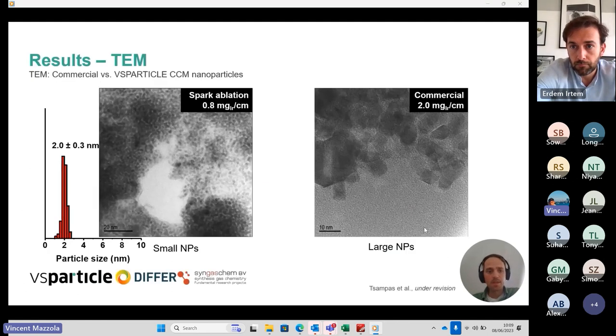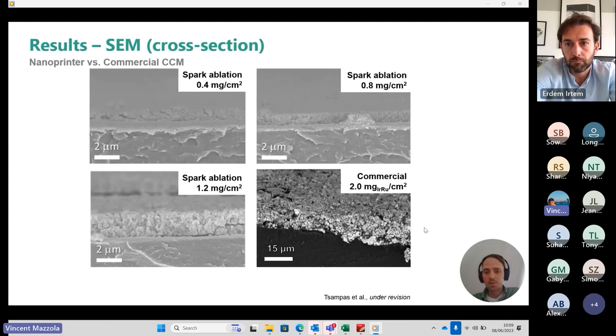To give you a bit of feeling on how this looks, here you see some initial results we have obtained together with Differ and have been published, and you can find the results also on our website. On the left, you can see that the nanoparticles printed by our technology are very small, in the order of 2 nanometer on average. And you see that they form a very unique nanoporous open structure. Compared to the commercial catalyst, they are much, much smaller and packed closely on top of each other. This is also the case if you compare our coatings to the state-of-the-art wet chemical coatings, in that we have a much thinner, much more homogeneous, much smoother surface that has beneficial effects on the performance of the CCM.